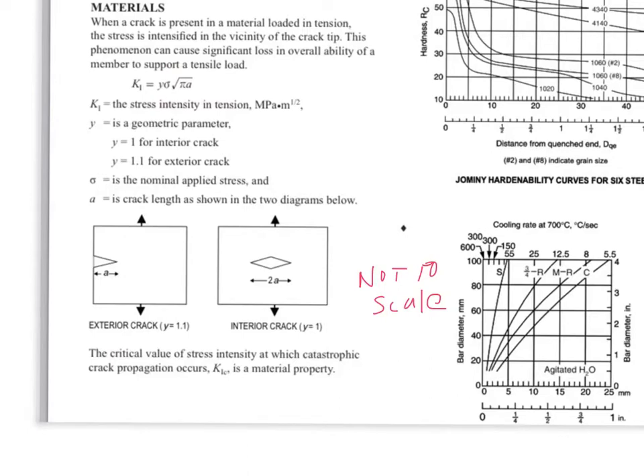So the model treats these cracks as having essentially half length of A, and you can see the full length of an interior crack is 2A, and this equation applies to both situations. So K1c, the stress intensity, is actually a material parameter, and what this equation tells you is when the conditions are such that this K1c value is reached by the combination of the stress, the geometric condition, and the size of the crack, you will have a brittle fracture in the material, regardless of whether it's ductile or brittle material.